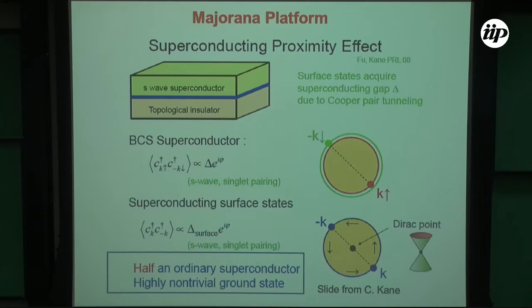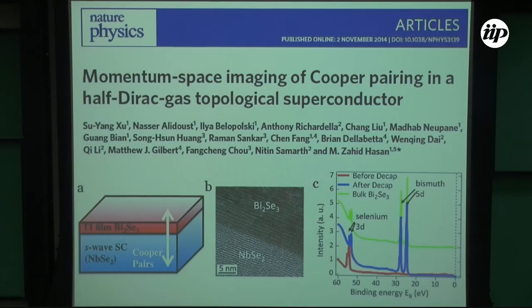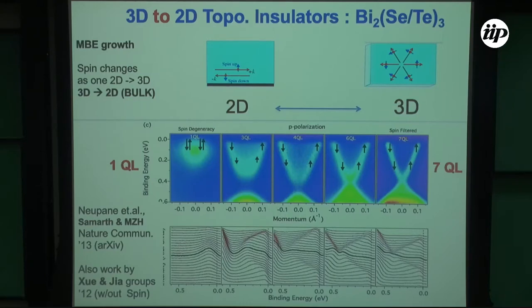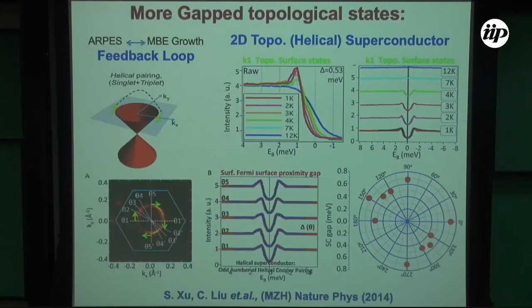It's very difficult to achieve these things with transport. You can do all sorts of transport, but you never know what is happening at the interface, because when you have a superconductor, be it at the interface or the bulk, all the Fermi surfaces will superconduct, all the states will superconduct. So our approach, this work is in collaboration with Nitin Samarth, is to study bismuth selenide films on top of niobium selenide, where you have superconductivity. We want to see what happens at the interface and also on the top surface. Because if it is thin enough, then you'll see the stuff in there. Again, we cap, decap, and then we have a diagnostic. We know which surface we're looking at. Again, this is how we figure out whether we are in the 2D limit or 3D limit, by doing spectroscopic checks.